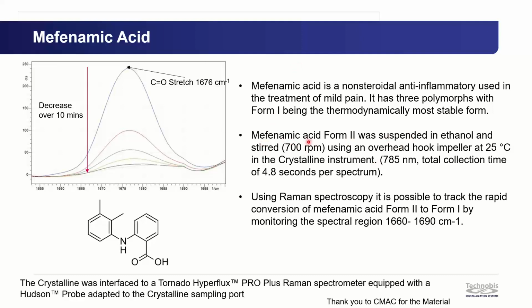So we were provided some mefenamic acid form 2, suspended in ethanol and stirred at 25 degrees C on the Crystalline instrument, which was then hooked up to the Tornado Raman. And we measured over 10 minutes the gradual decrease of the stretch at 1676 wavenumber over time until eventually it's no longer present, and we've fully converted to form 1 over the space of 10 minutes.